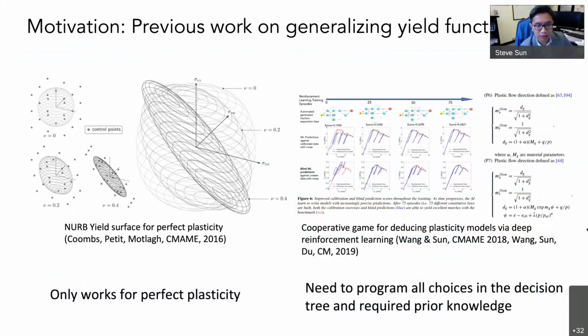In that particular case, this technique is applied to identifying the yield surface, parameterizing the yield surface. So you can think about that. The most straightforward way to generate a constitutive law is to create a learning problem where we have a strain history to predict the stress. However, if we incorporate the plasticity framework, what we want to do is that if we know the elasticity, the plasticity constitutive law could be complete if we know how the yield surface evolves in the stress space. With that assumption, we can consider the constitutive law modeling problem as a geometry problem.